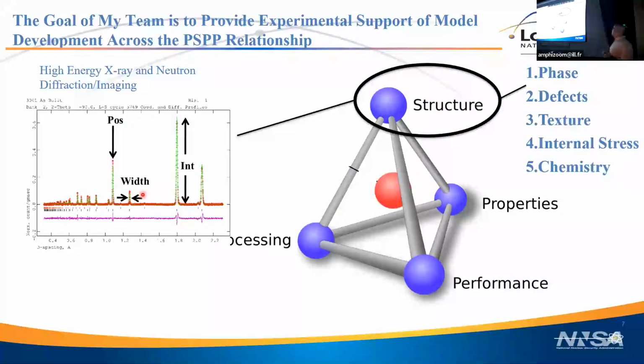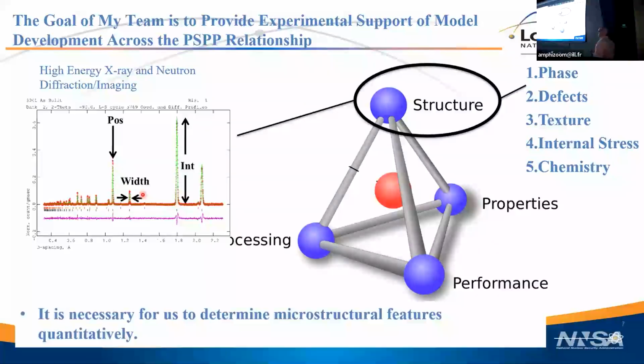Once we have that structure, then we want to relate it to the actual quantitative microstructural parameters. And this is a very important point to me. If you're going to walk out of my talk with one point today, this is it. At Los Alamos, it's extremely valuable that we come out with quantitative microstructural features. We need to come out with a dislocation density, not a peak width. We need to come out with a phase fraction, not a peak intensity.